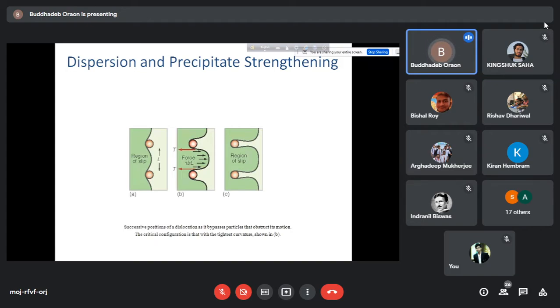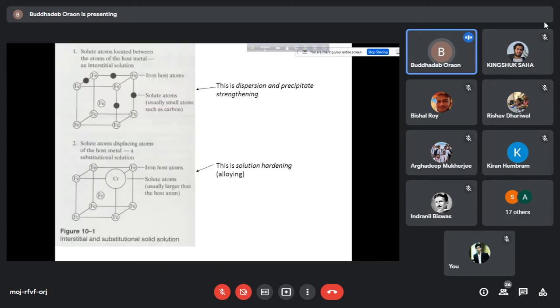Now this is another way of looking at it: how dislocation movement or slip can be resisted with the help of solute atoms mixed within the volume of the material. Dispersion strengthening and solid solution hardening, there is a difference. When you replace a regular iron atom, let us say, and mix in, let us say, chromium, this particular iron atom gets removed and this chromium atom is added. This we call substitutional solid solution, and this is called solution hardening. Whereas when the solute atoms take an interstitial position, we call it dispersion or precipitate hardening.